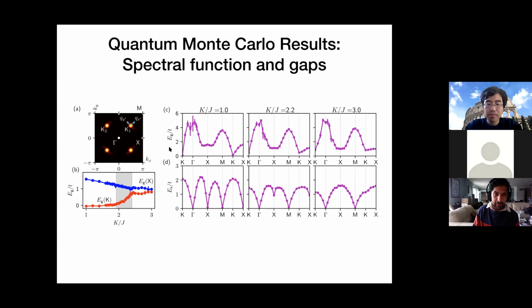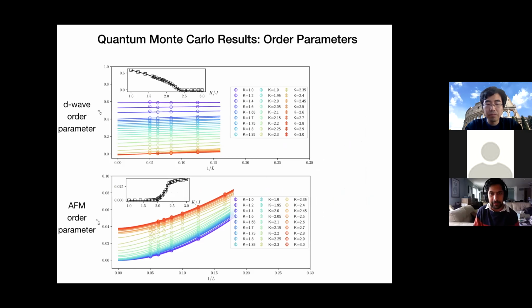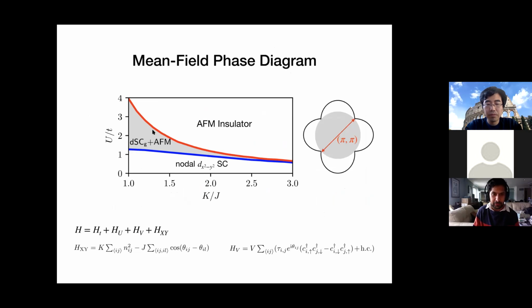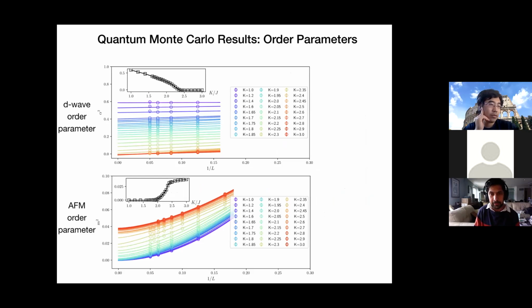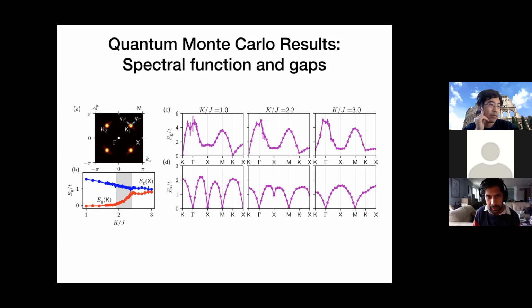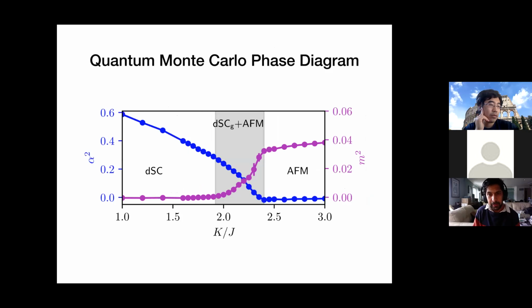This is the gap for the electron. This is the spin gap. So you can also see the magnons in the antiferromagnetic phase. So everything is what you would have expected based on the low energy theory of these phases. So no surprises, but the point is you can get this physics without a sign problem. And this is the phase diagram.